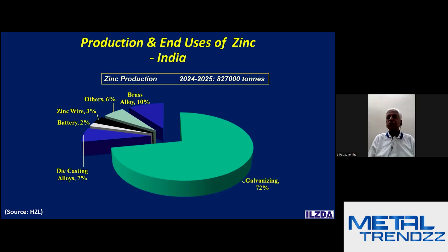A lot of homework to be done on the die casting front. Zinc wire is around 3%. Zinc wire is used for thermal spraying. I was just now talking to you about zinc spraying. Next to hot dip galvanizing, zinc spraying is the largest market. You have a spray gun where you put zinc wire or zinc powder, melt them, and the molten metal deposits will be projected on the steel surface. That's your sprayed zinc coating, unlike the hot dip galvanized coating.